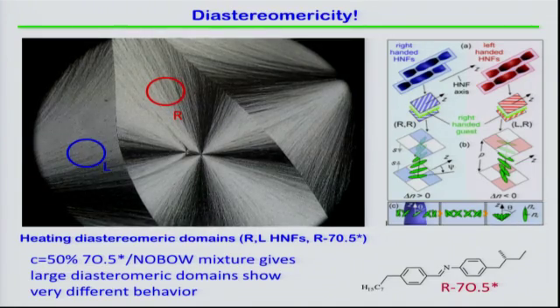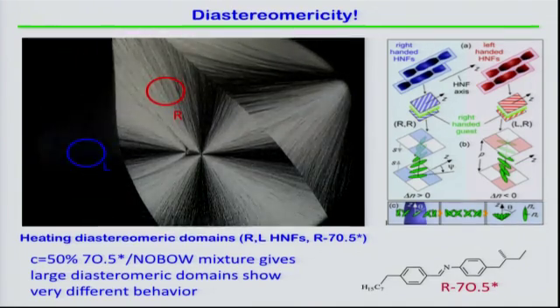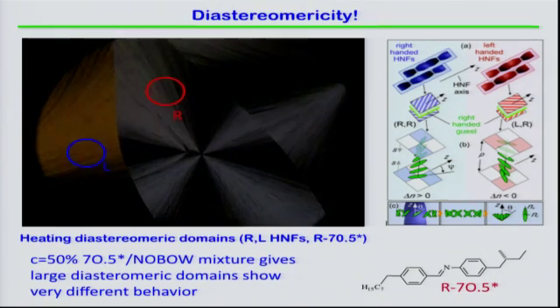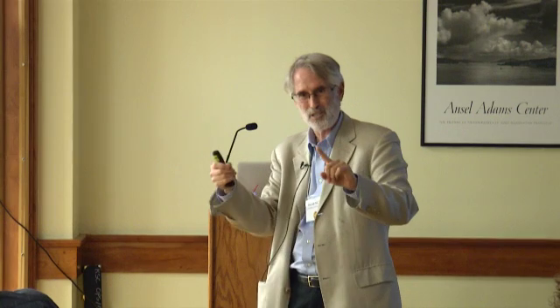So let me try to heat the sample. There we go. One of them extinguishes. Then they both come back out of extinction, and then they extinguish totally. Okay? So that's this diastereomeric behavior that you expect when you have left-handed, right-handed, and right-handed, right-handed. Those things behave differently. And what it is, the nematic aligns on the surface of the helical nanofilaments in a very specific way. The nematic twist is always the same, but you can have right-handed or left-handed helical nanofilaments, which are sort of mirror image related.